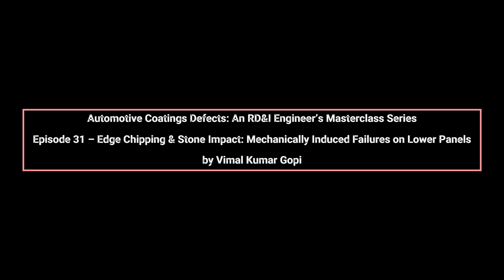Substrate support and geometry are crucial. Lower panels often experience more flexing due to chassis dynamics and road vibrations. Panels made of thinner steel or aluminum experience higher deflection under load, increasing the effective tensile stress on the coating. Weld seams, hem flanges, and complex geometries amplify these effects, creating predictable chipping zones. OEM engineers conduct finite element simulations and real-world testing to identify high-risk areas and validate coating performance under mechanical loading.